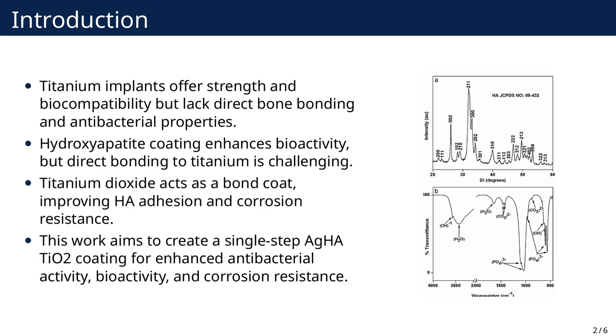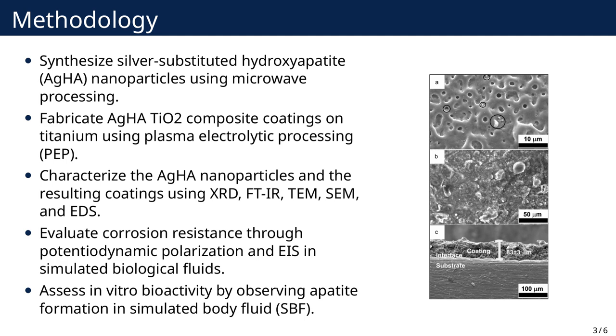Hydroxyapatite (HA) coating can improve bioactivity but has challenges in chemical bonding with titanium due to different lattice structures and material properties. Silver-substituted hydroxyapatite (AgHA) nanoparticles were prepared using a microwave processing technique. Analytical grade calcium hydroxide, diammonium hydrogen phosphate, and silver nitrate were used with a calcium plus silver to phosphorus molar ratio of 10 to 6. The synthesis involved microwave irradiation for 30 minutes, followed by washing, drying, and powdering.